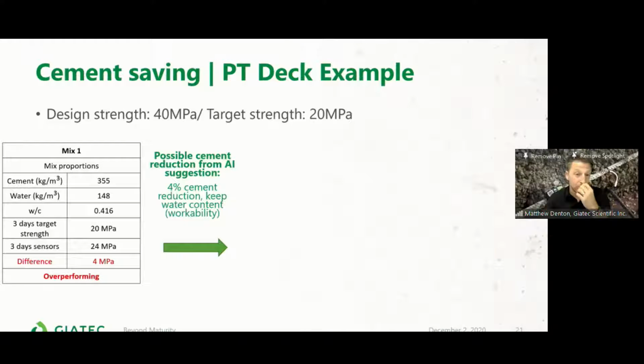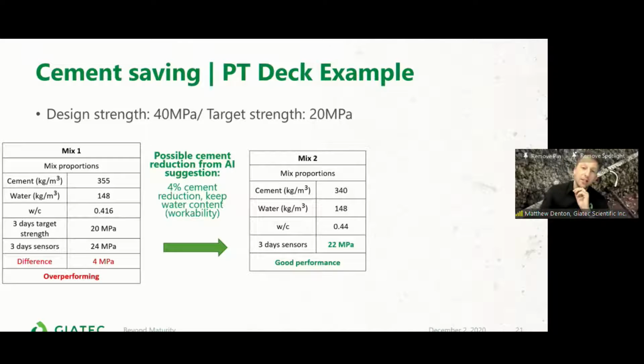What did this allow us to do? This allowed us to put this information into our system, into our AI, into our 360 dashboard, and our AI was able to spit out the information that we could actually reduce the cement by 4% and keep the water cement ratio. So we kept that workability. We didn't want to affect that, but we wanted to see how we could reduce the cement that was actually put in here. This allowed us to come out with a different cement value of 340 kilograms per cubic meter. Our water stayed the same, so our water cement ratio changes just a little bit there.